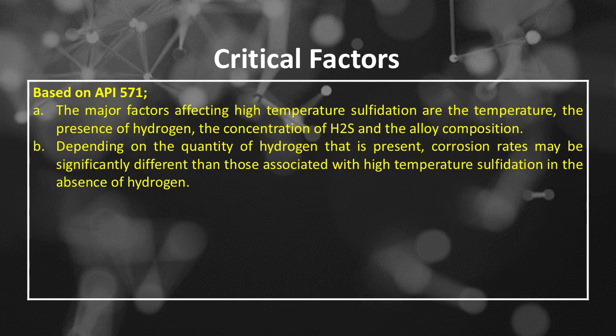Number A, the major factors affecting high-temperature sulfidation are the temperature, the presence of hydrogen, the concentration of hydrogen sulfide or H₂S and the alloy composition. Number B, depending on the quantity of hydrogen that is present, corrosion rates may be significantly different than those associated with high-temperature sulfidation in the absence of hydrogen.